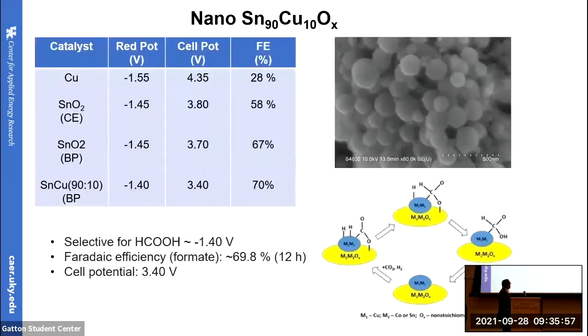Further, we synthesized copper tin oxide nanocomposites. These are the pictures. When we introduce copper into tin, the particle size of the nanoparticles is further reduced. We got it comparable to 100 nanometer particles using this copper tin, and these were used at different potentials, and we got very good formic acid formation at an even lower negative potential, that is 1.40, with close to 70% Faraday efficiency in 12 hours. Here I have given the comparison of the results.